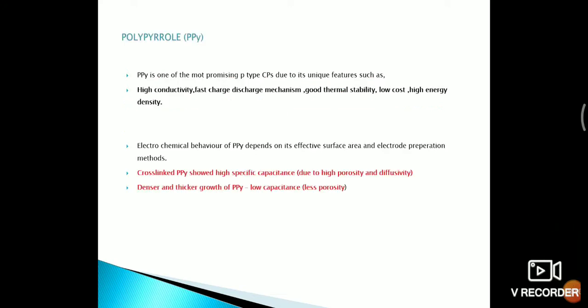Next one is polypyrrole. Polypyrrole is one of the most promising p-type conducting polymers due to its unique features such as high conductivity, fast charge discharge mechanism, good thermal stability, low cost, high energy density. Electrochemical behavior of polypyrrole depends on its effective surface area and electrode preparation method. Cross-linked polypyrrole showed high specific capacitance due to high porosity and diffusivity, whereas denser and thicker growth of polypyrrole showed low capacitance due to its less porosity.